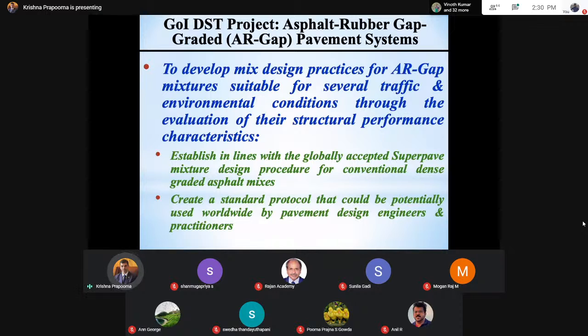We had the Government of India Department of Science and Technology project when I was at IIT Kharagpur for about 3 years. In this 3-year project, we developed a mix design procedure and implementation plan for asphalt rubber gap. I'm talking about asphalt rubber only, not CRMB. CRMB is a different blend, the 8 to 12% I told you about. It does not fit into the ASTM definition. Whatever I talk about from now on is asphalt rubber, meaning a minimum of 15% crumb rubber by weight of asphalt cement.